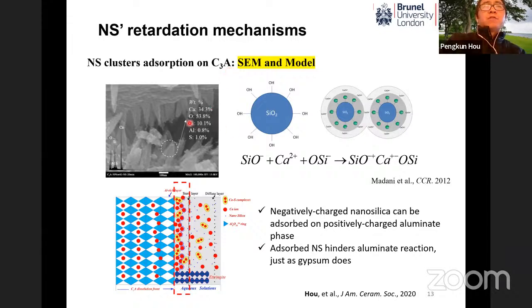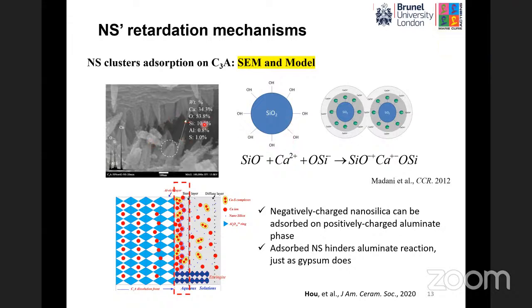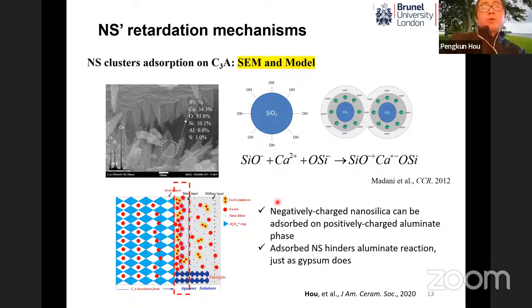And actually, this kind of structure, you can see it like a stalagmite and stalactite on the C3A particle, is formed by the bridging of the nanoparticles, which are negatively charged, by the positively charged calcium ions, forming the stalagmite structure. So from this, we can conclude that the negatively charged nanosilica particle can be adsorbed on the positively charged C3A aluminate phase surface, which will then hinder the aluminate reaction, just as the gypsum does.